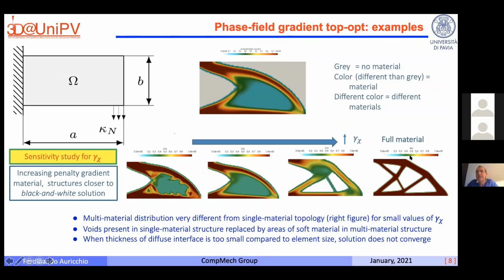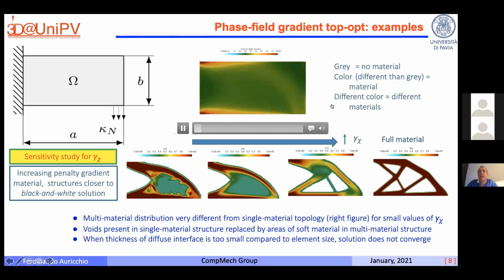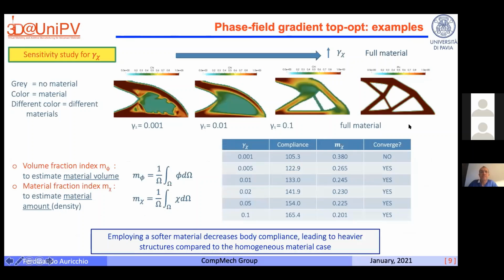So if you really increase this parameter, you will obtain a structure with a single material, which is the classical result from topology optimization. But if you relax the constraint on the gradient of chi, you can obtain a solution like this where you have basically graded material. You can clearly do parametric studies, and here I'm reporting some numerical results. And really, the basic concept is that by changing the constraint on this second field, you can obtain a structure which shows different compliance, but at the same time also different weights.